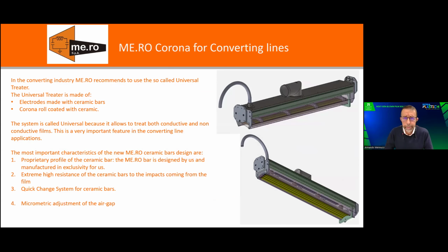Okay, we have talked about treaters for cast film lines. Now we focus on the second topic of today, which is the corona treater for converting lines. When I say converting lines, I mean corona treaters for printing lines, flexo or rotogravure, laminating machines, extrusion coating machines, or coating lines in general. So here we recommend the use of a completely different corona system, where the concept is reversed. We bring the dielectric on the electrodes, and so we do not have the dielectric on the roll as on the extrusion lines.